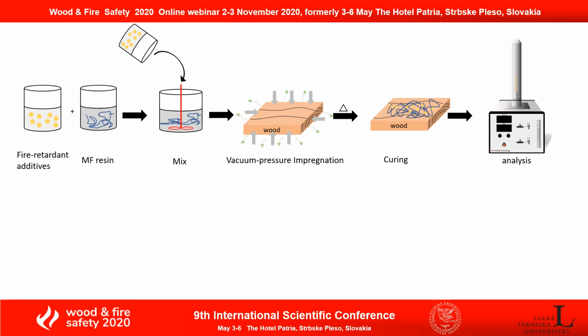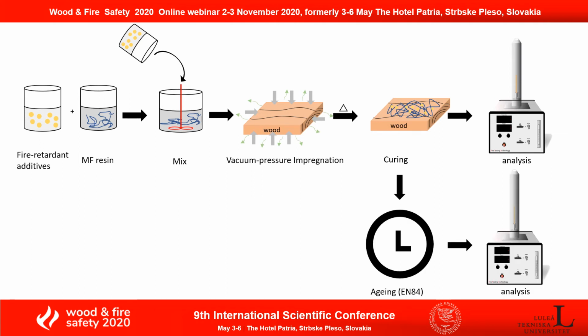And after that, I used the limiting oxygen index to analyze its fire performance. And also because I want to understand if these fire retardant additives are stable within the wood matrix, I applied the leaching test EN 84, which means the samples were soaked in water for 14 days and the water was changed 10 times in between. And after that, the samples were removed from the water and dried, and then I analyzed their fire performance and compared the results before and after EN 84.